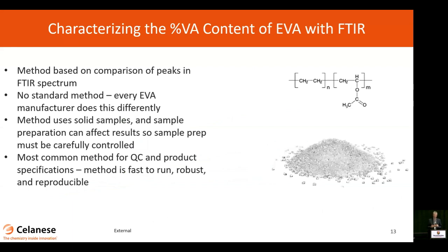So we have to be pretty thoughtful about how we characterize it. The standard way that you're going to see people characterize vinyl acetate content for product release, for product specification purposes, is going to be with some sort of FTIR method. There are standard methods that are published that no one essentially uses. So in practice, everyone has their own method that they've validated and they've used for, in our case, 40 years.